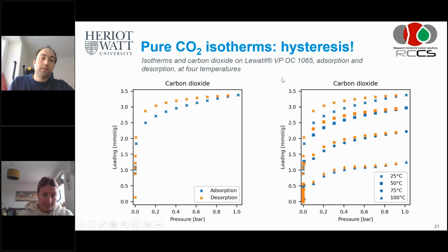Well, what the isotherm says is how much CO2 is on the material at a certain pressure, right? So if we look at the partial pressure of 0.4, for instance, what our results say is that if you are in the adsorption mode, then your loading is a little bit lower than when you're in the desorption mode. At first, we did think that potentially that was a result of improper or incomplete equilibration, but we tested and tested and tested again. And every time we saw in the dynamic graphs that the uptake was completely flattened out, so the system was equilibrated. Now, what this means is that, for instance, if you adsorb CO2 onto your material and you go all the way up to 1 bar, and then you start desorbing, you start reducing the pressure again.